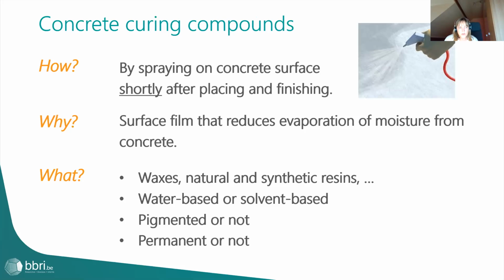One of the easiest ways to cure concrete in place of conventional and prolonged wet curing is to apply a liquid curing compound on the concrete surface. How to do that? By spraying the product immediately after placing and finishing for a floor or a slab, or of course after demolding for vertical surfaces. When correctly applied within recommended dosage, it forms a surface film that reduces evaporation of water from concrete. These chemical products are mainly waxes or resins emulsified in water or solvent. They can contain pigments that are useful to check the cover area and also to provide heat reflectance. But be careful anyway, as most curing compounds have to be removed prior to applying any coating.